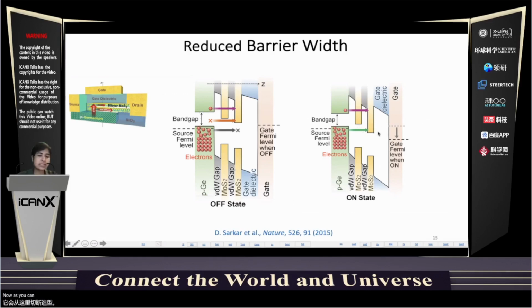Now, as you can see here, the width through which these electrons have to tunnel is given by these 2 layers of molybdenum disulfide. 2 layers of molybdenum disulfide is extremely, extremely thin. Each layer is 3 atoms in thickness, so 2 layers is 6 atoms in thickness. So the tunneling barrier can be made atomically thin, in this case, only 6 atoms.